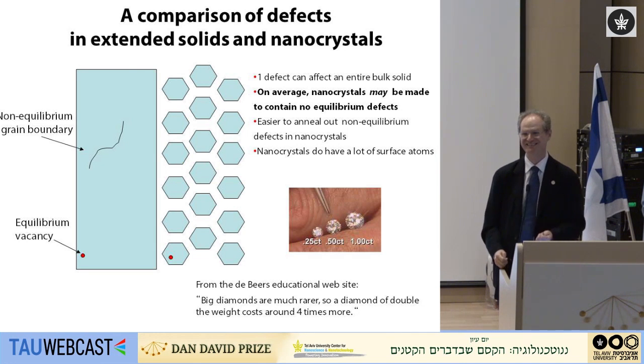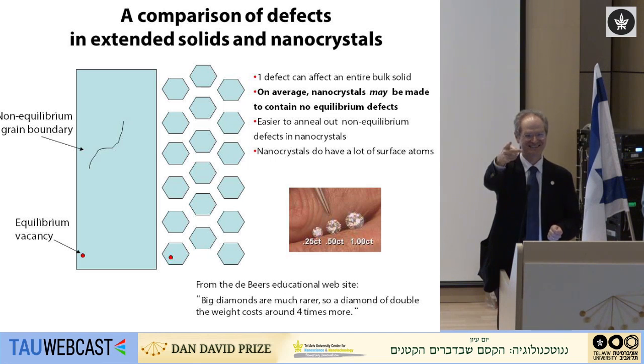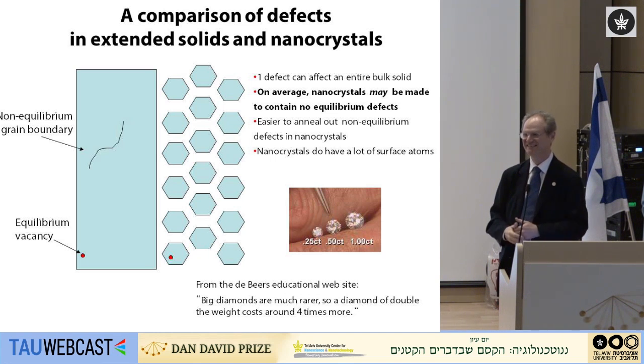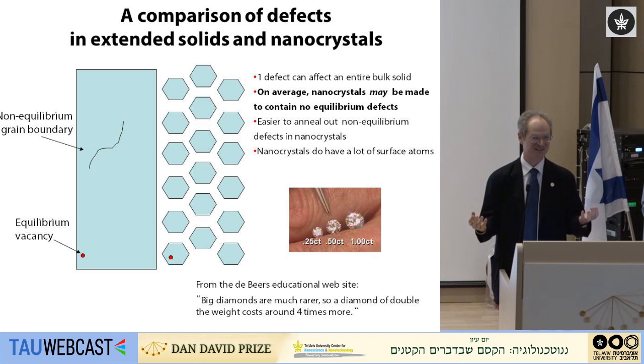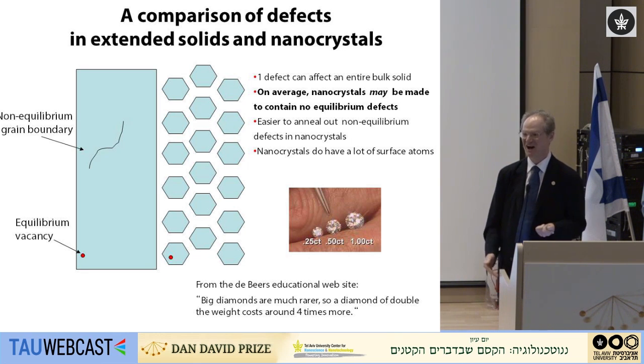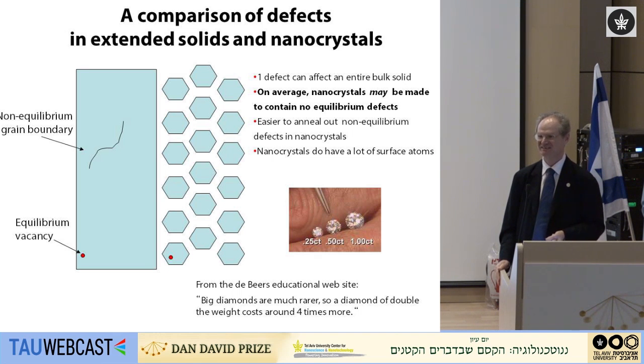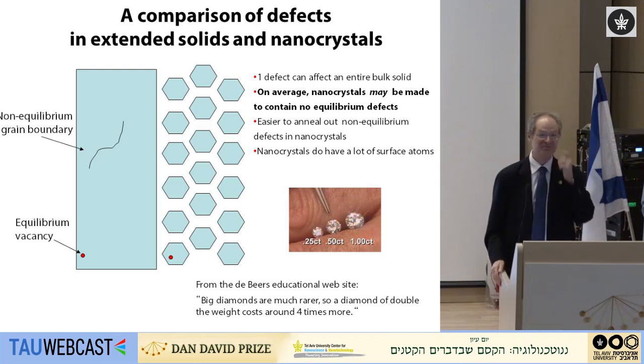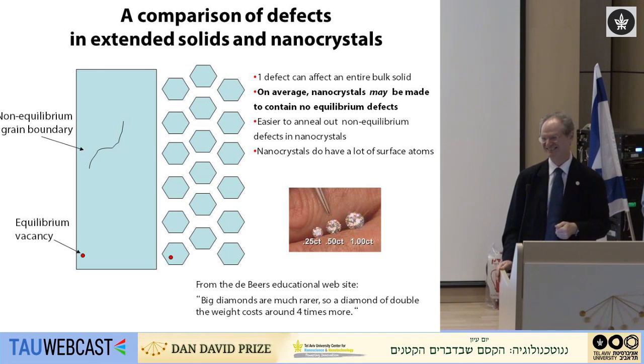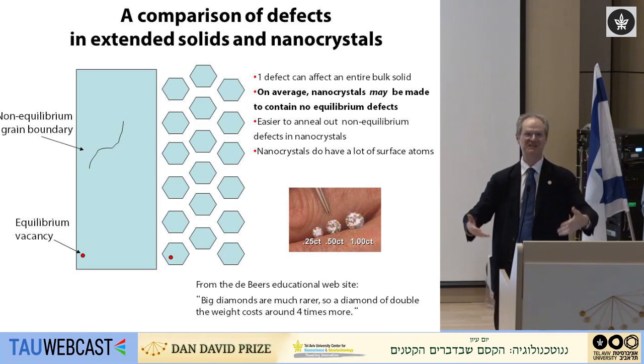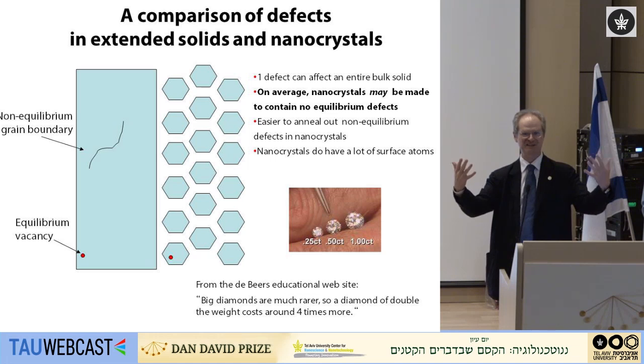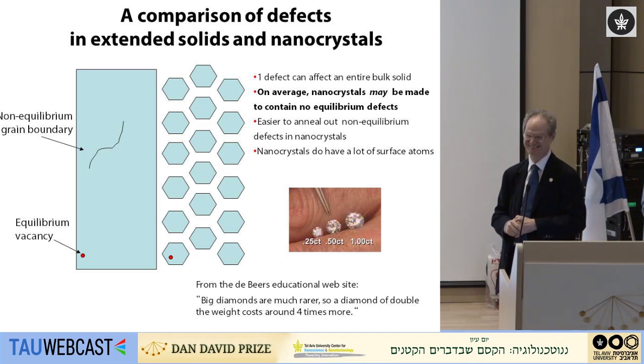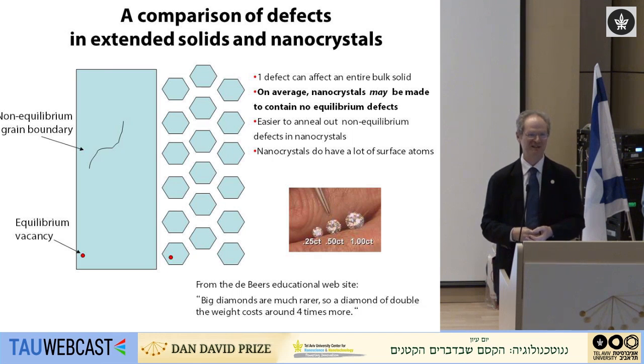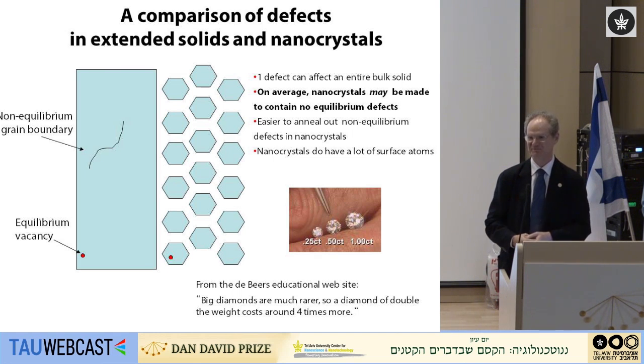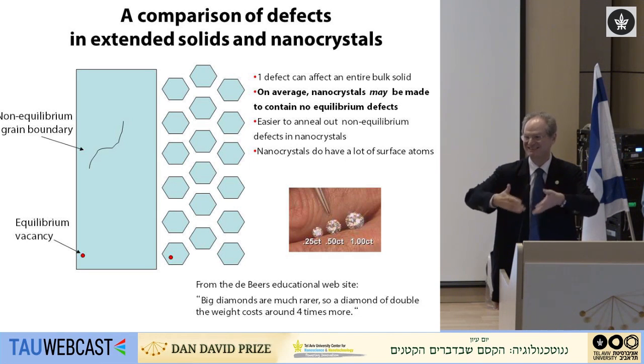Well, in nanoscience, we turn that on its head, upside down. We say, okay, if that's true for a really big crystal, what if my focus is on a really tiny crystal? If it's only 10 atoms across, the time to anneal a defect out is actually much less than a second. And in fact, because the melting temperature is low, what I just showed you a minute ago, I can take a material which ordinarily has to be made at a very high temperature under very complex chemical environment of extreme purity, and instead I can take that material and grow it under very, very simple conditions at a low temperature. And the defects will simply go out to the edge.